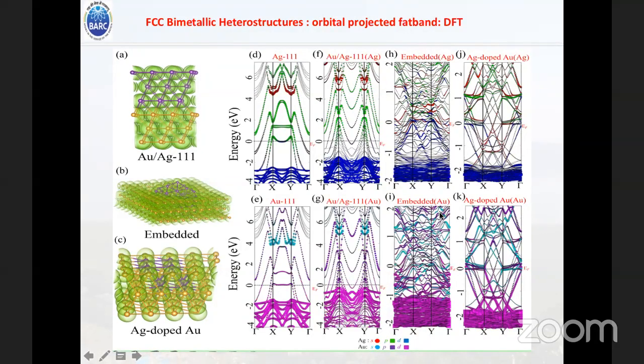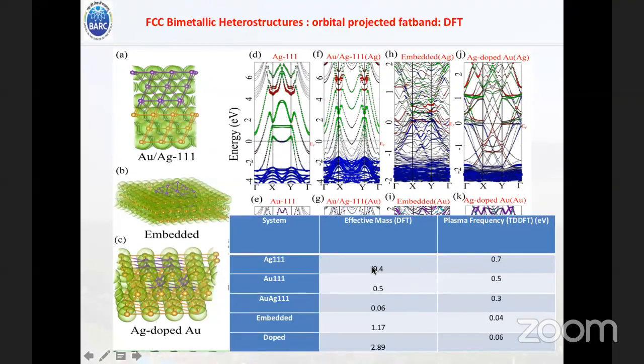So now we have calculated the effective mass for this system, and we have seen here Au and Ag, these are the effective masses. For Au-Ag111, you can see that there is a reduction of effective mass. So there was some earlier data for this Au-Ag large area interfacial system by Satish Ogale and others. They have shown that there is no advent of any kind of correlated behavior for these kinds of systems. That is quite understandable, because all the bands here have simply Fermi liquid nature.